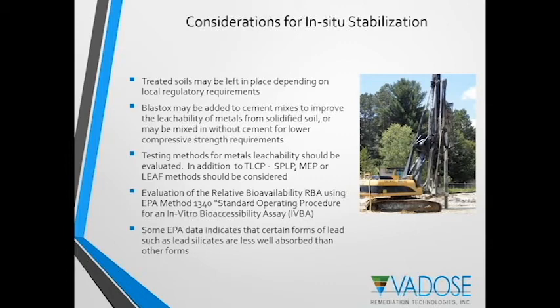You can also evaluate treated soils for bioavailability using Method 1340, a standard operating procedure for in vitro bioaccessibility assay. So this is a way to demonstrate that stabilizing these soils will reduce bioavailability of the metals. And then finally, as just related to that, the EPA has some data that has indicated that certain forms of lead, such as lead silicates, are in fact less well absorbed than other forms. So it's good to know that complexing the lead with an agent such as calcium silicate can reduce uptake of these contaminants.